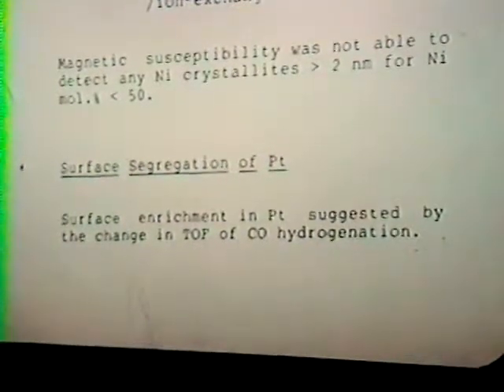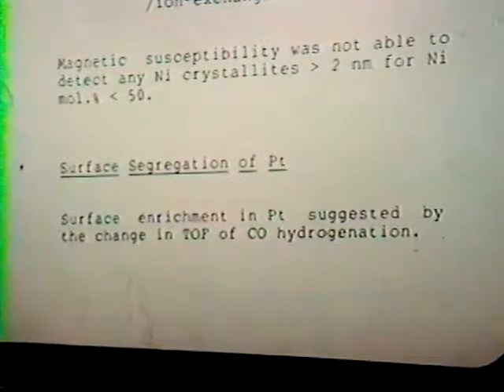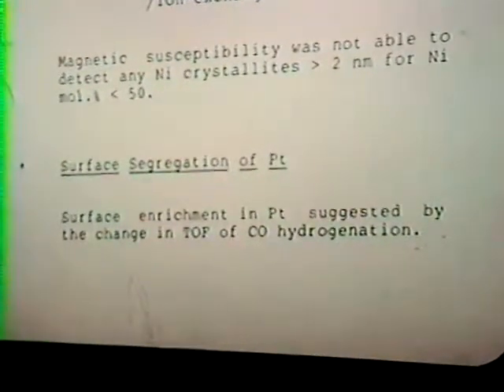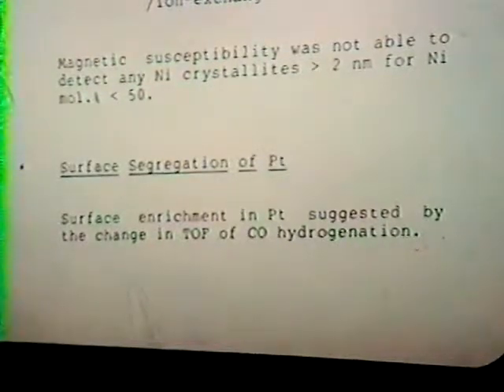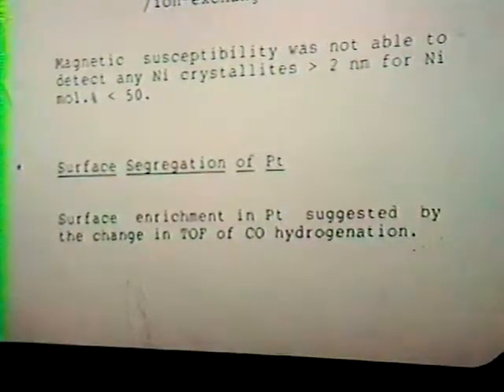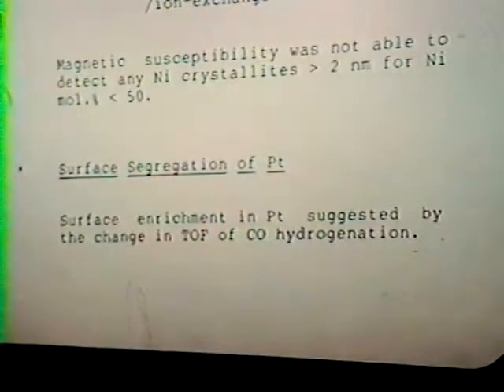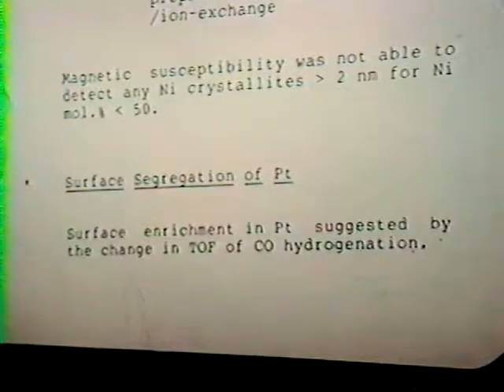In adding a noble metal promoter to a base metal system, if you're trying to achieve a better base metal catalyst, you would probably want a noble metal which preferentially stays in the bulk of the particle and does not preferentially segregate, in order to prevent deleterious effects on the reaction properties.